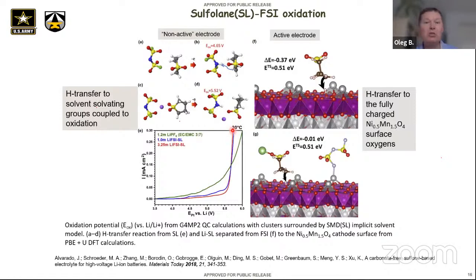That's on non-active electrodes. What happens on the active electrodes, which can accept protons? Marco Olguin did this calculation. He found that sulfolane next to a high voltage spinel surface has a favorable H transfer energy with a barrier of 0.5, which indicates quite a fast reaction. If sulfolane is bound to lithium, this barrier for transfer stays about the same, but the reaction becomes less energetic. So at high concentration, we will have a little bit of these reactions, but much less favorable than what happens at low concentration. So concentration will play a role, but why is there still an improvement? Some of them are still going to be decomposing.